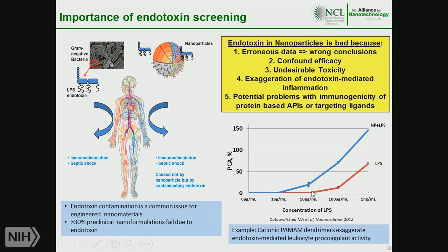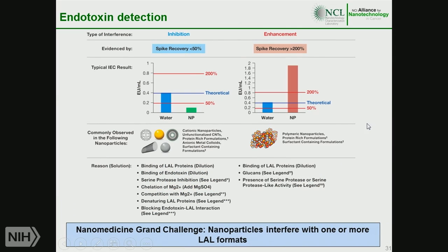This is the induction of leukocyte procoagulant activity by pure LPS, and LPS is the main component of the endotoxin. And alone, the red line, and the blue line shows the effects of the same concentration of LPS in the presence of one concentration of nanoparticle. This concentration of nanoparticle is unreactive. It doesn't cause procoagulant activity induction. So you see that we are looking at the enhancement.